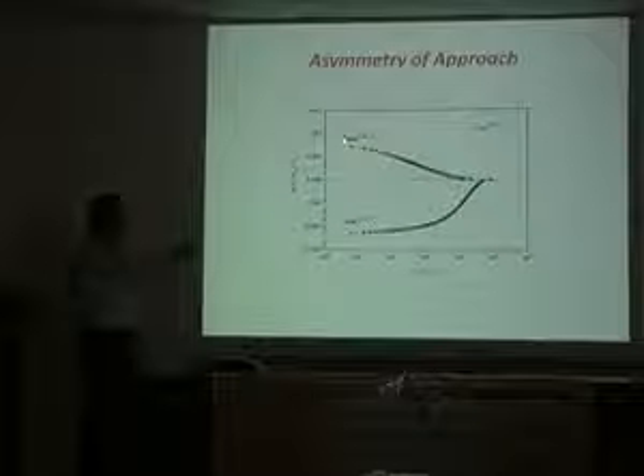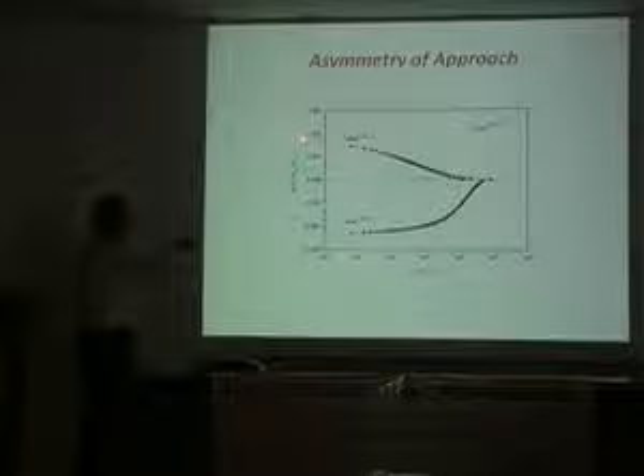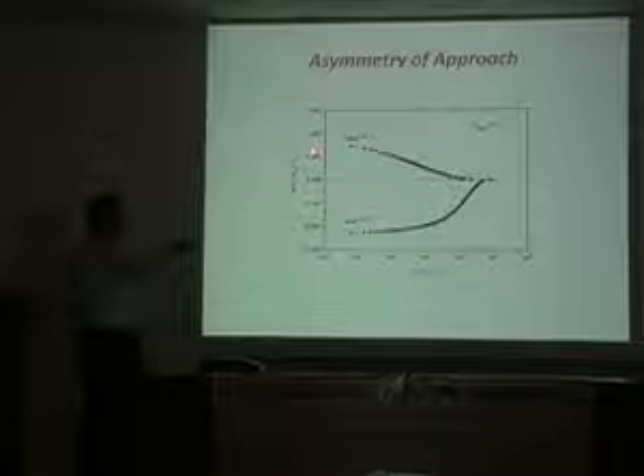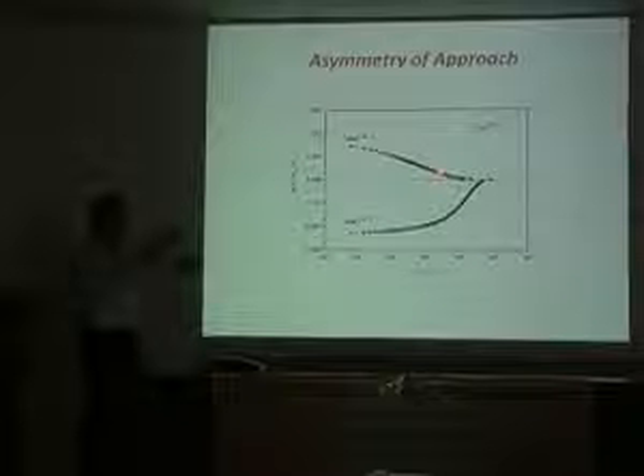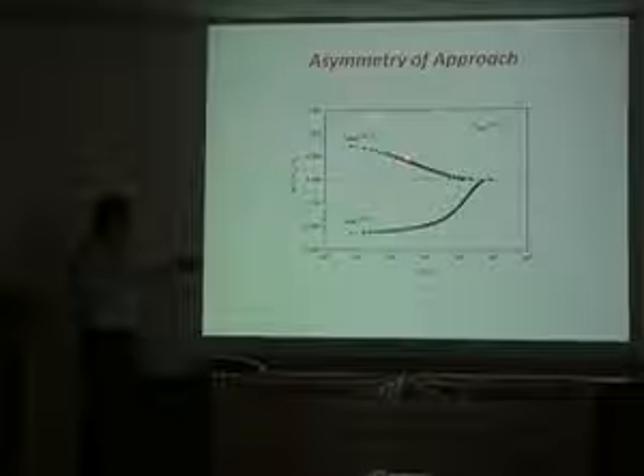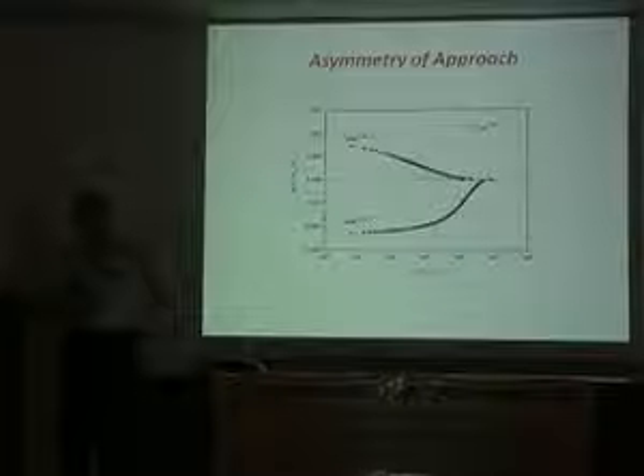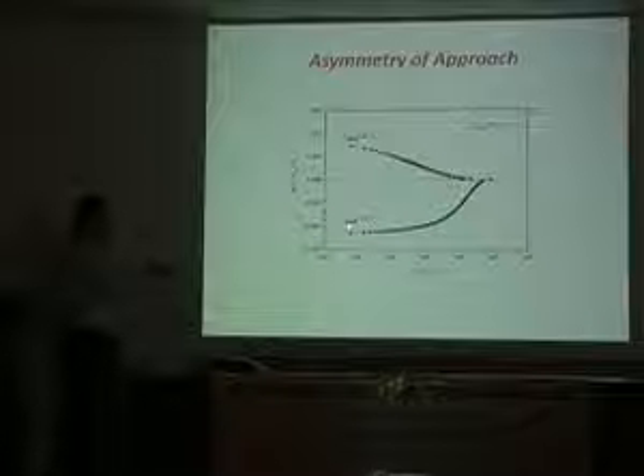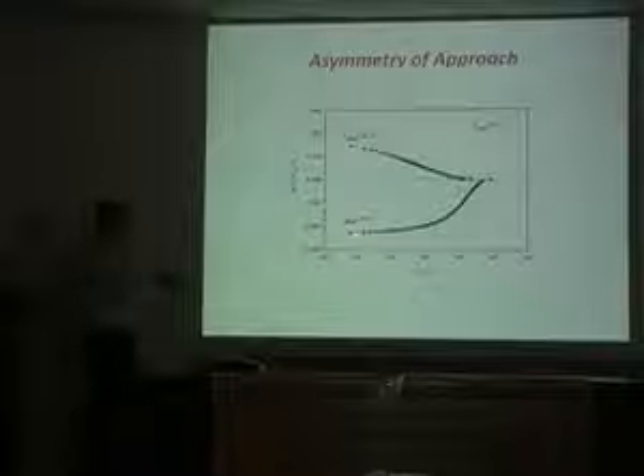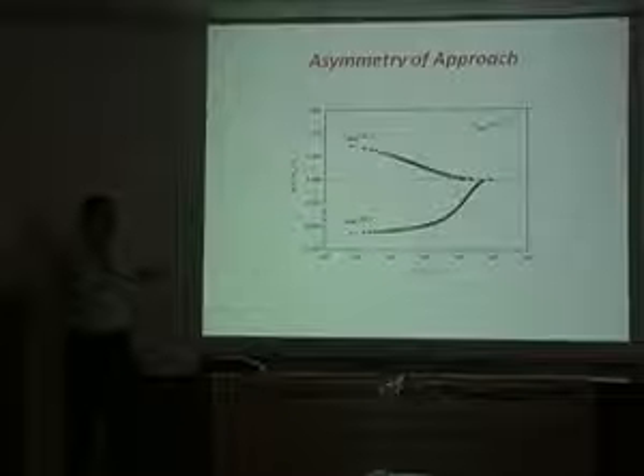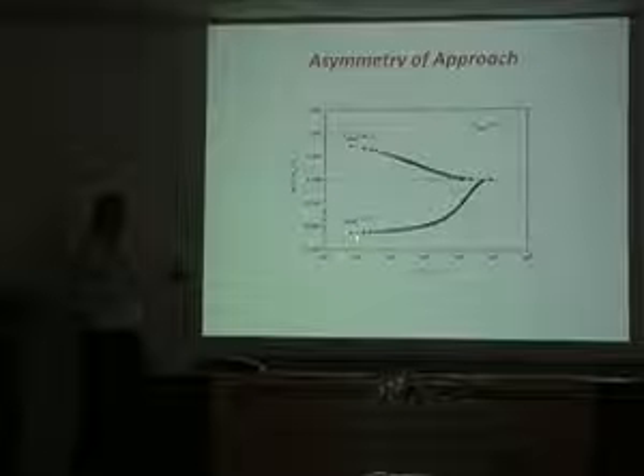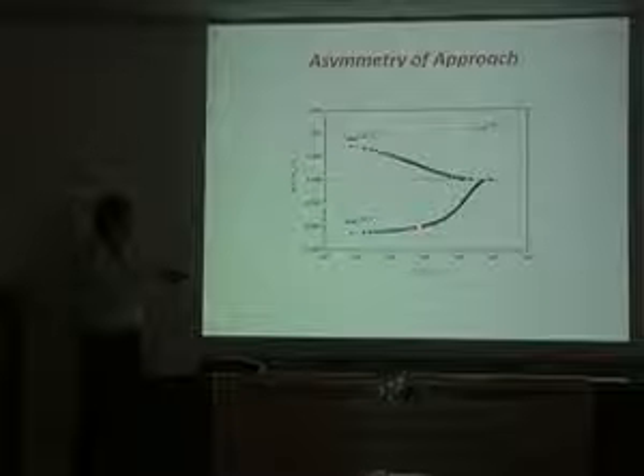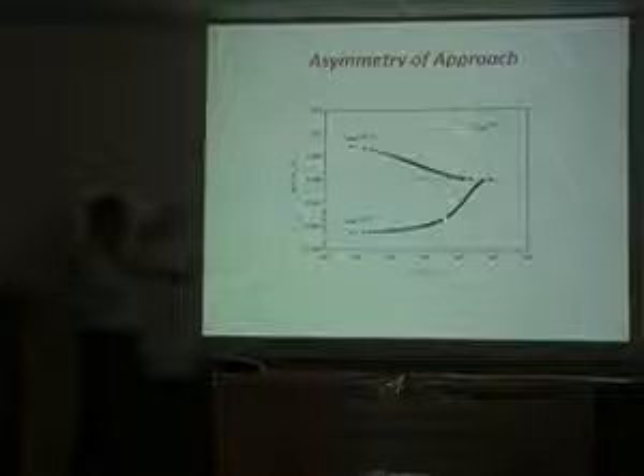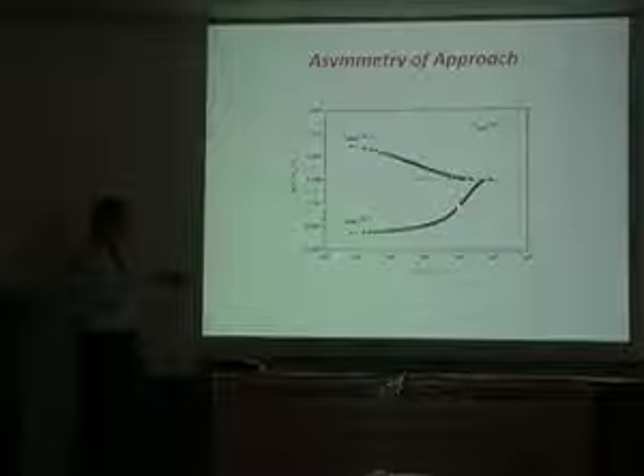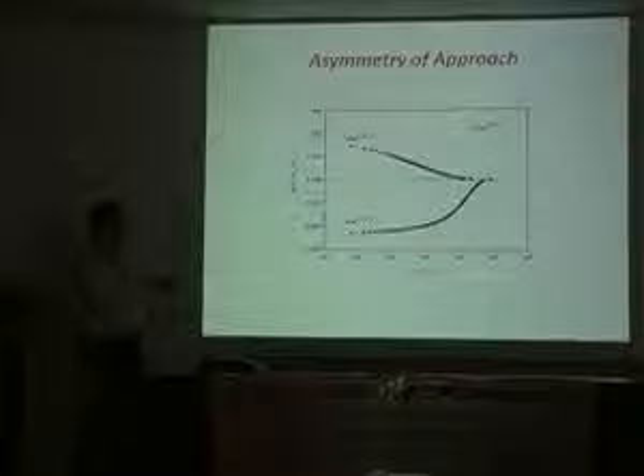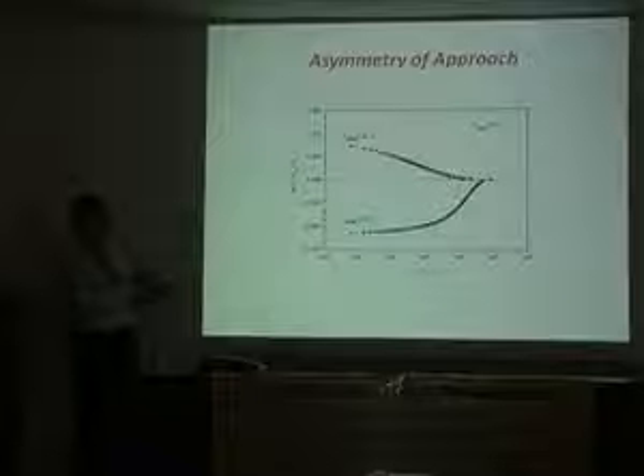And when I did the quench, they very rapidly evolve and then get slower and slower as the density increases, and come into equilibrium in what looks sort of like an auto-retarded process, is how Kovacs called it. In the up jump experiment, you start off with a deficit of this excess volume, a negative excess volume, so a deficit of volume. So things are crowded and it's moving very slowly to come towards equilibrium. And eventually, as the volume goes up, it starts going faster and faster and then gets into equilibrium in sort of what looks like an autocatalytic process. It's not really autocatalytic, it looks like it on this log plot.